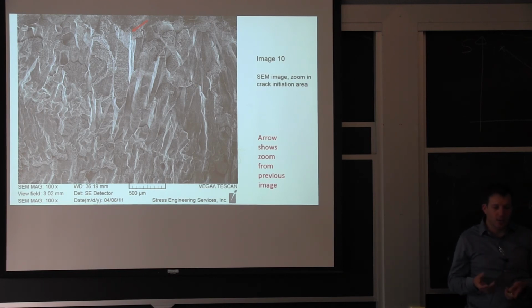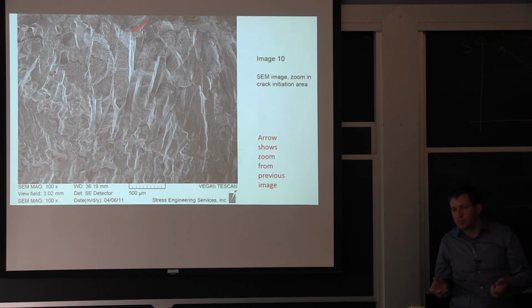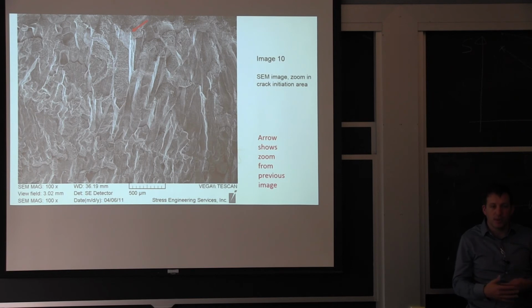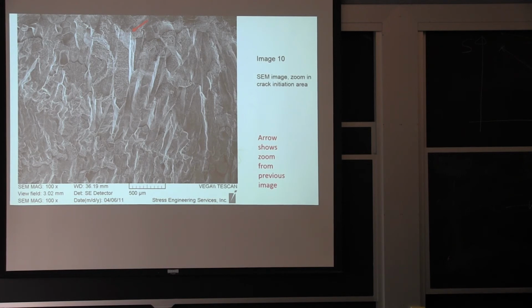So that hydrogen is preferentially going to the grain boundary because it's an open space. And then it facilitates, reduces the strain, and you can get the cracks to go through there at pretty high speed. You know, it's not super fast in this case. You still need the time for the diffusion of the hydrogen to get ahead of the crack and just start growing it.